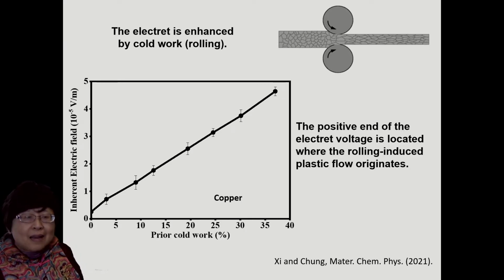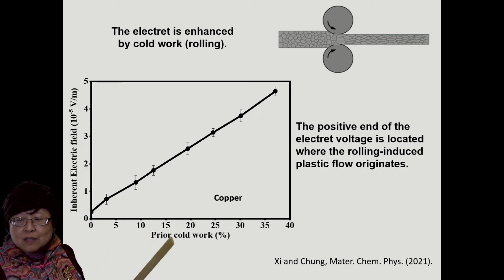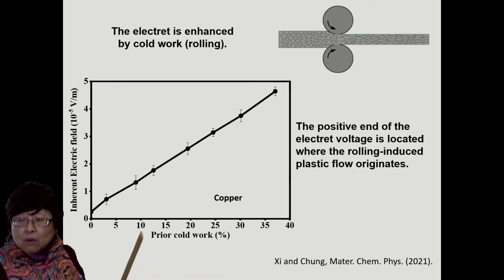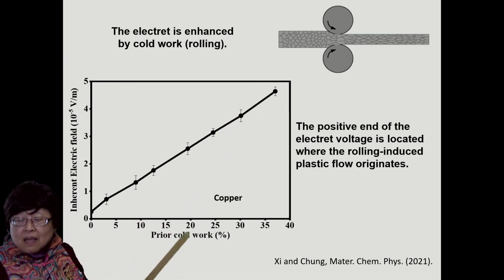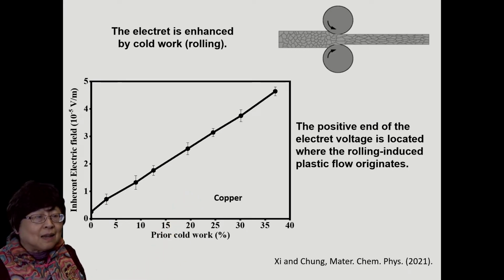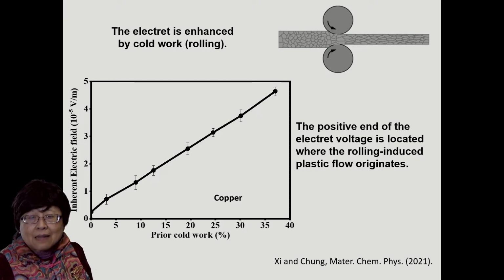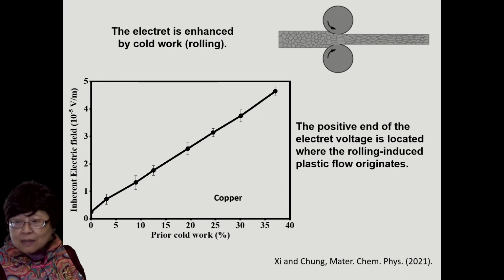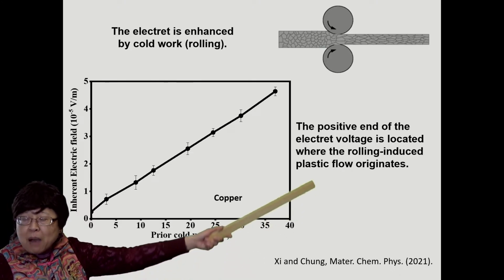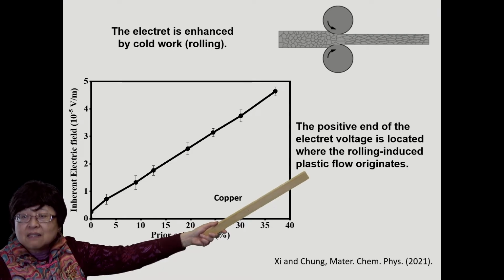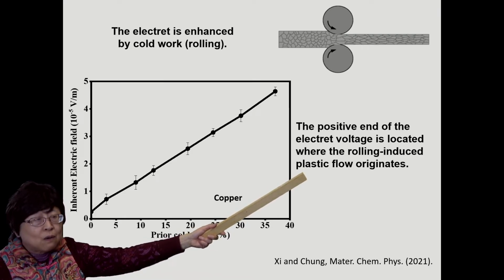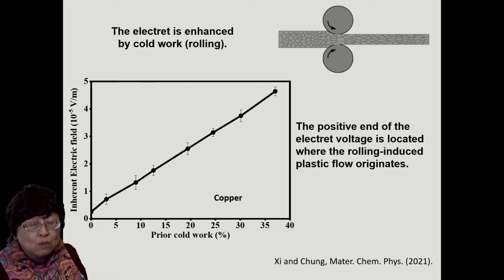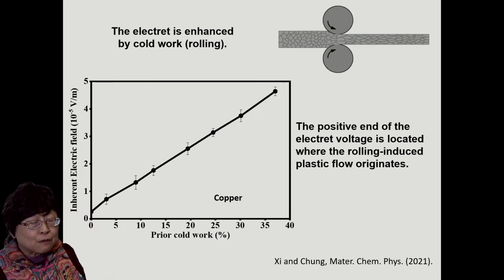Now, the cold work that I mentioned before not only increases the permittivity, it increases the electret voltage too. This is the electret's electric field versus the amount of prior cold work for copper. The cold work, again, involving cold rolling. Again, it's electron-atom interaction that's enhanced by having more sites for that interaction. But very interestingly, the positive end of the electret voltage is located where the rolling-induced plastic flow originates. That means the electrons move along with the atoms during the plastic flow, a clear indication of electron-atom interaction.